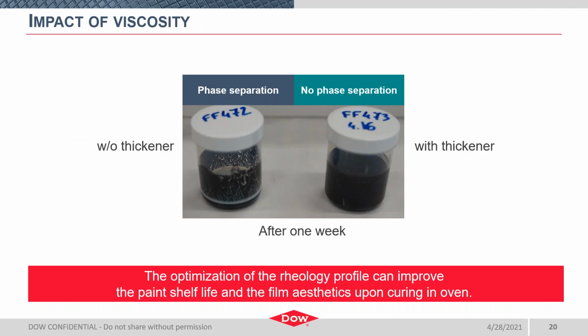As typical in water-based paints, adding a rheology modifier improves the stability of the paint. There are two samples shown. The left does not include a rheology modifier, and the right sample here does include that ASE 60 rheology modifier. Without the thickener shown in the container on the left, phase separation is observed, which in turn could impact your film homogeneity and aesthetics and would probably require more mixing before use.